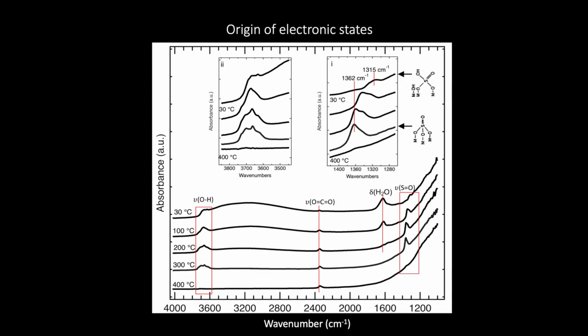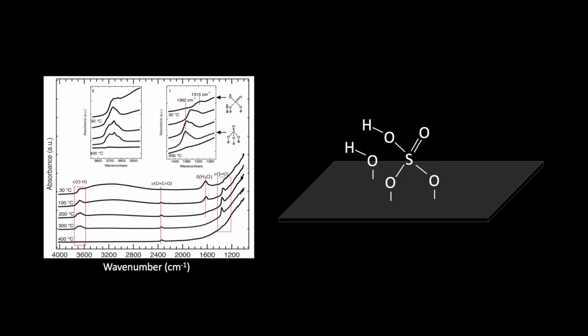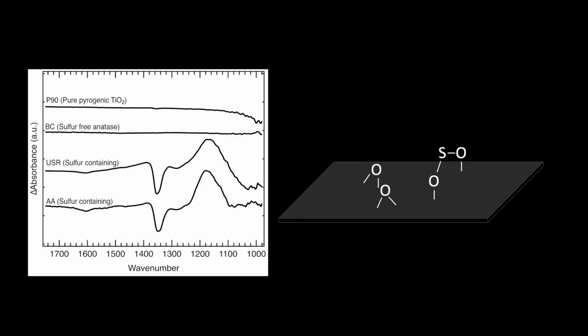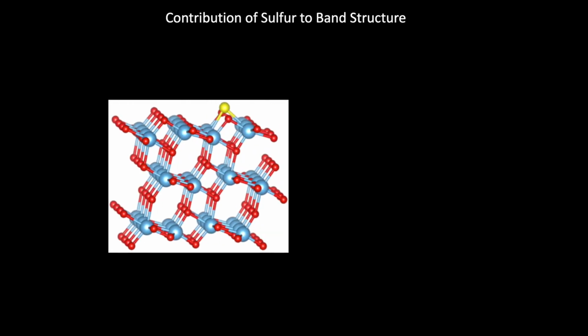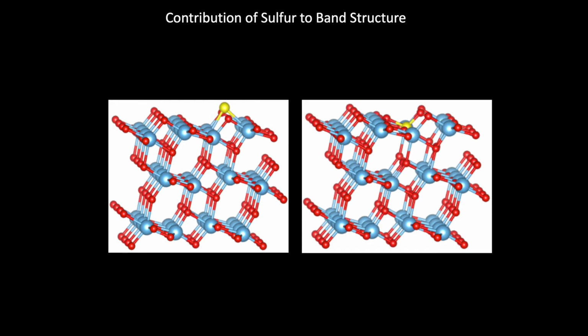Monitoring the surface with FTIR during the pretreatment step shows that the bidentate sulfate-like species transfers into a tridentate structure at 300 Celsius while the surface is dehydrating. Our finding shows that there are no deep traps created at this point. Heating the surface further at 400 Celsius results in reconfiguration of sulfate-like structures and creation of lattice-substituted sulfur. In all cases that we observed deep traps, sulfur was present in this form. These findings suggest that the origin of these deep electron traps is sulfur atoms substituted into the lattice.